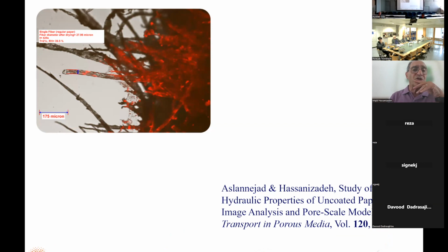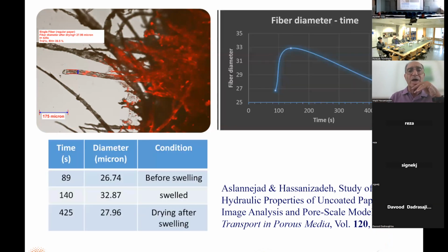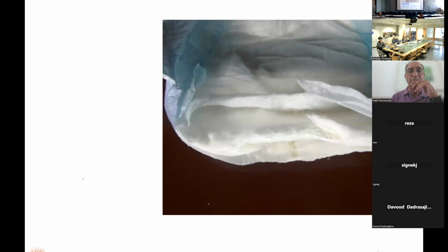We can also measure the thickness of the fibers. They swell as the liquid comes in. On the right-hand side, this is time in seconds, and this is the single fiber diameter, this particular fiber actually. You see that the thickness grows by 20–30%, and then it reduces again as the paper dries and the ink evaporates. And you can see the numbers here as a function of time.